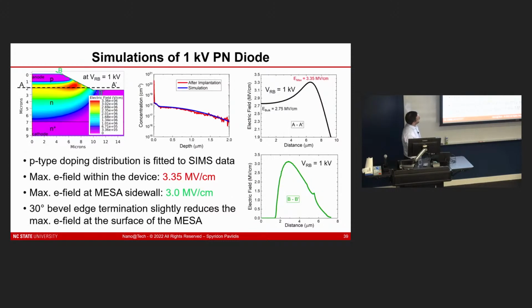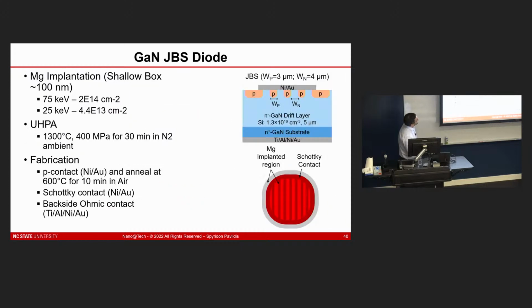And so before I get to that, I just want to show that my student did some modeling here to try to understand what the distribution of the electric field is. He also tried to match the simulated distribution of magnesium to what we had through SIMS, so it was kind of a better representation. And you're able to see that we're getting critical electric fields that are near the ideal in that 3 to 3.3 range for GaN. So we're leveraging the GaN at its maximum here. So this is very recent work. It's actually just been published.